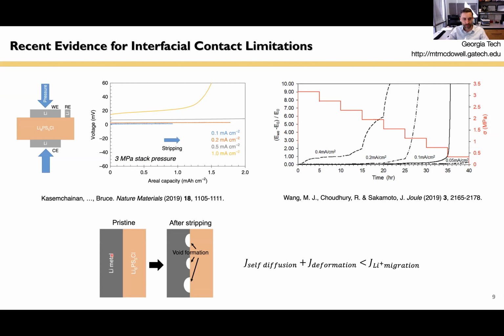And you can visualize this down here with this schematic. If you have lithium metal in contact with a solid electrolyte and you oxidize lithium metal, what you're doing is you're converting these atoms to ions and they travel through to the right through the solid electrolyte. But when you do that, you're removing lithium atoms from the lithium metal electrode. And so something has to come, another lithium metal atom has to come and take the place of that atom because you formed a vacancy. If you don't have replenishment of the lithium at the interface, then you'll eventually form voids at the interface, which is basically a contact loss mechanism, which can lead to very bad things, which I'll show you.